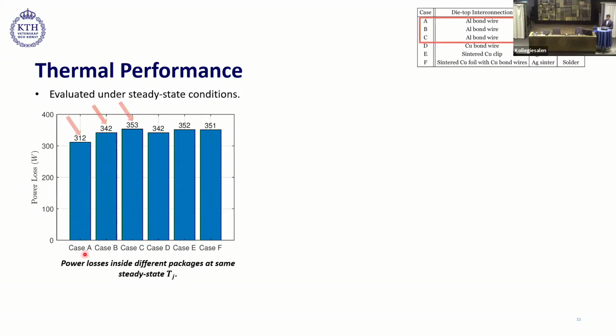If we focus on the first 3 cases, we see that we have, say, aluminum bond wire on top, but the die attach and the base plate attach material is changing. And we observed that by replacing solder material with silver sinter, we have better thermal performance. If we also focus on case E and case F, then we see that introducing copper clip on top or copper foil also improves the thermal performance a bit.